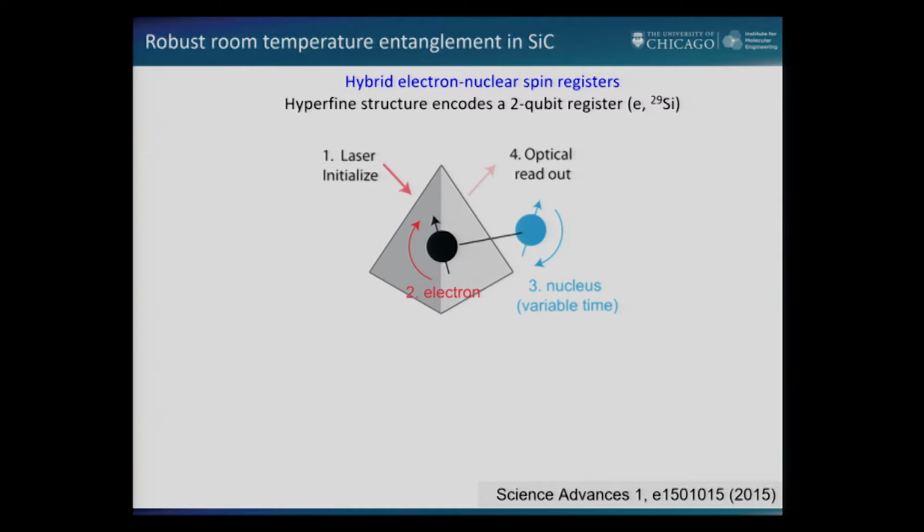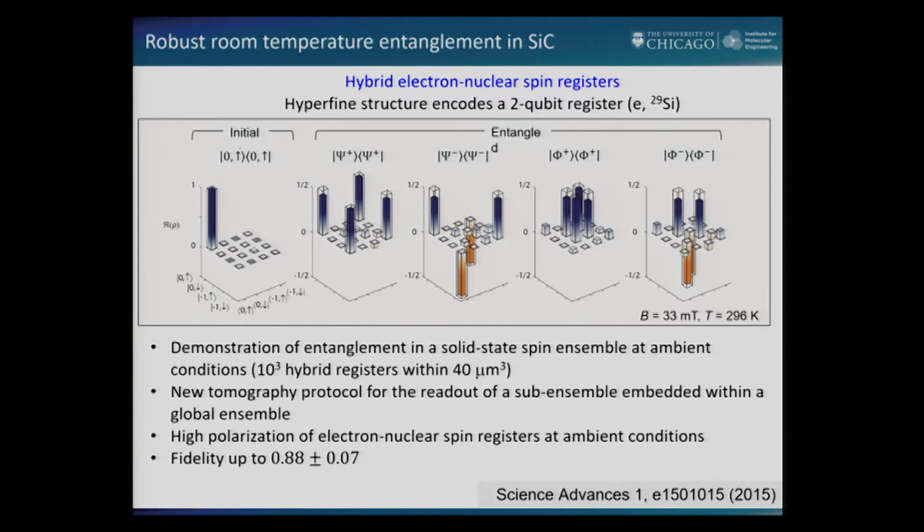They're basically disordered materials. You grow nitrides on top of them with a small oxide layer for processing, and these same materials have quite high nuclear polarization. So the fact that you can prepare spin-polarized electrons and now polarize the nuclei very efficiently, both of which are somewhat unusual to be able to do in the same material, means that if you excite them simultaneously, you can entangle them. You have an electron spin, you have a nuclear spin, which is usually quite difficult to manipulate at the single spin level. And Paul Klimov showed relatively recently that if you do this properly, you excite the pair, you can create ensembles of entangled states at 300 Kelvin in these wafers.